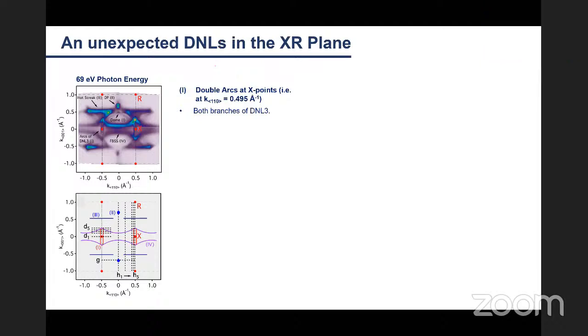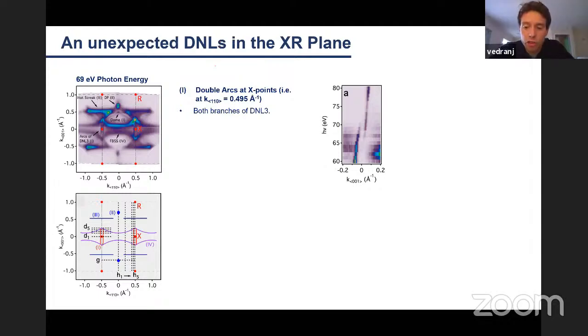So first and foremost, we observe a double arc structure centered at the X points, and they are the two branches of the Dirac nodal line that forms the third, DNL3. The arcs extend towards the zone center, and are restricted to a very narrow range of photon energies, which you see in the middle here. So essentially, you really had to hit this narrow range to see both of these arcs in the same window. And this is shown in this momentum dispersion curve.